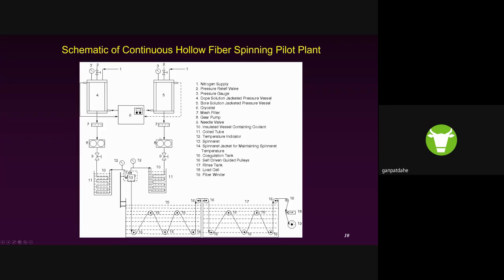All this setup was temperature controlled, so one can get a consistent result irrespective of the temperature outside or in the room. At the spinneret, as soon as the polymer solution and the coagulant contact each other just below the spinneret, the precipitation or phase separation process starts. There is a diffusion of non-solvent into the polymer solution, and of the solvent into the non-solvent. During this phase separation, it forms a polymer-rich and a polymer-poor phase. The polymer-poor phase leads to pore formation, while the polymer-rich phase leads to the solid structure formation, the polymer matrix. This is how the pores are created in the hollow fiber.